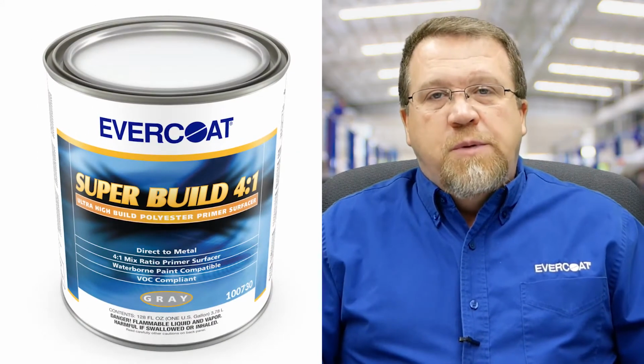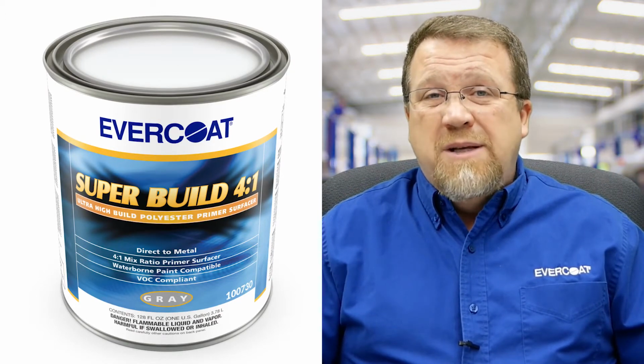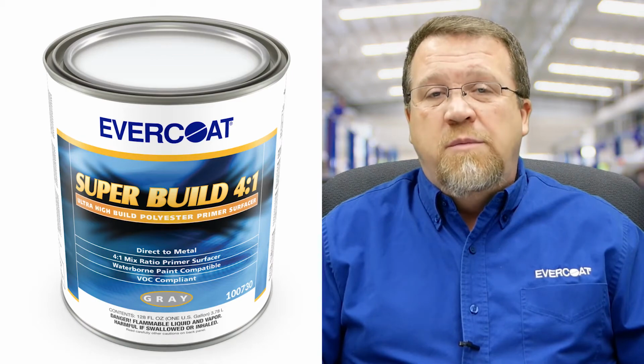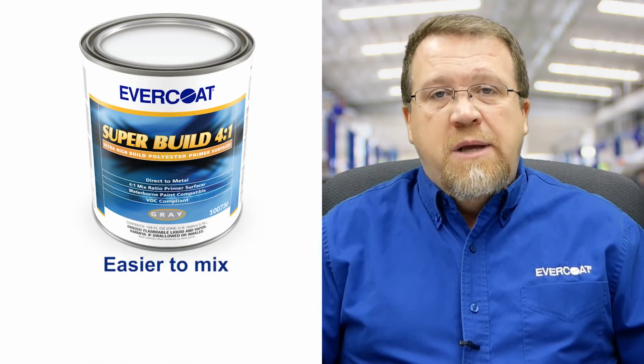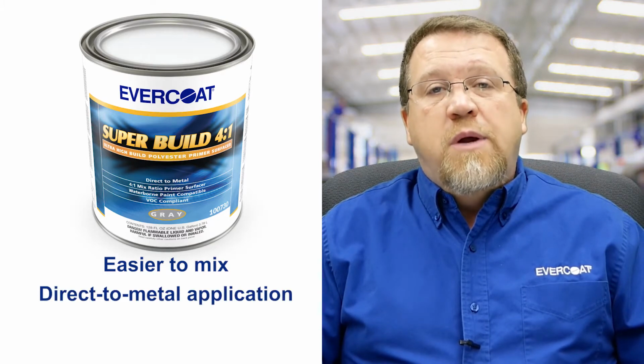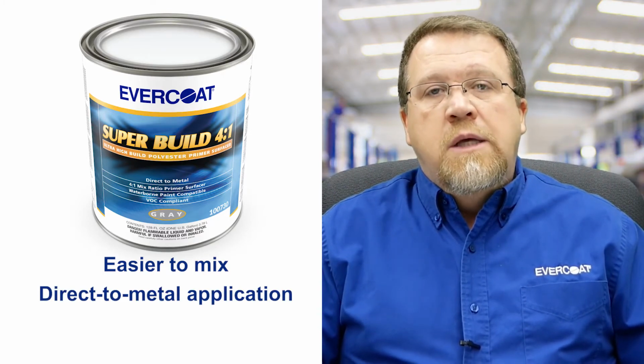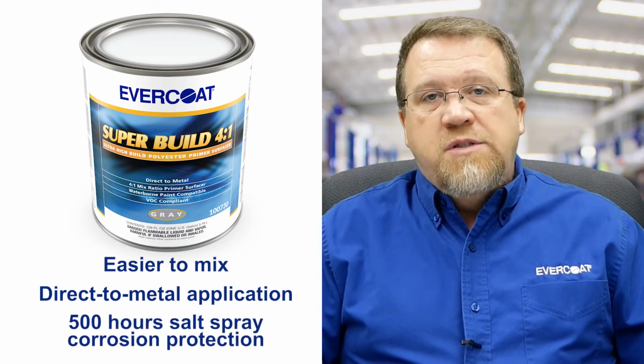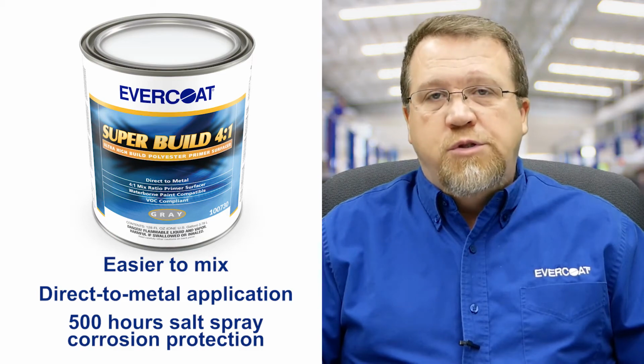Our original Super Build is actually mixed at a 4-to-1 ratio. Traditional polyester primers had been mixed at a 50-to-1, so it was very difficult to mix. With a 4-to-1, it's much simpler to mix. We also incorporated a direct-to-metal property, so it can go directly onto bare metal. It meets the ASTM B117 standard testing methodology for 500 hours of salt spray corrosion protection.